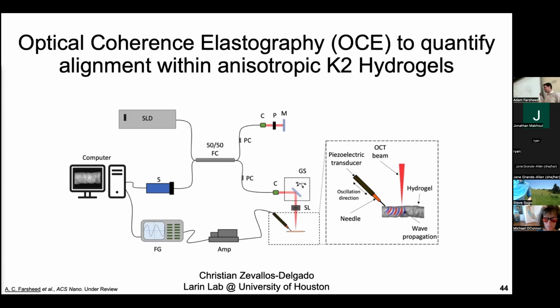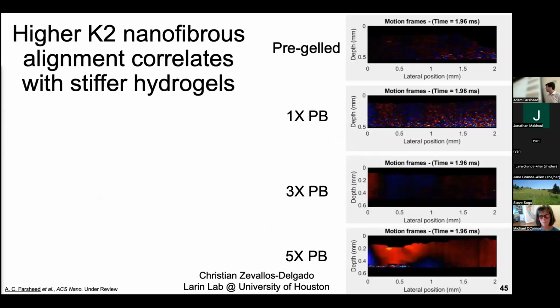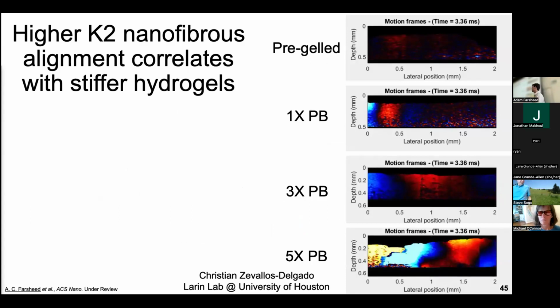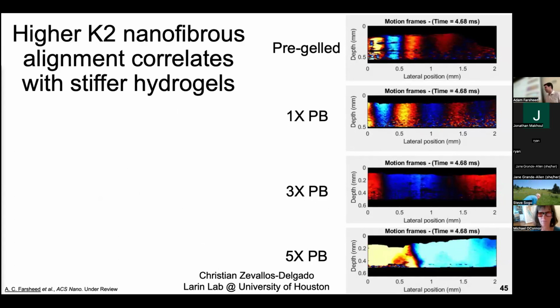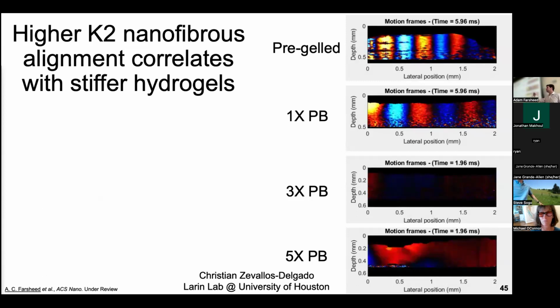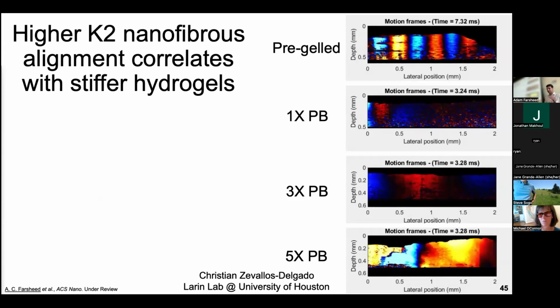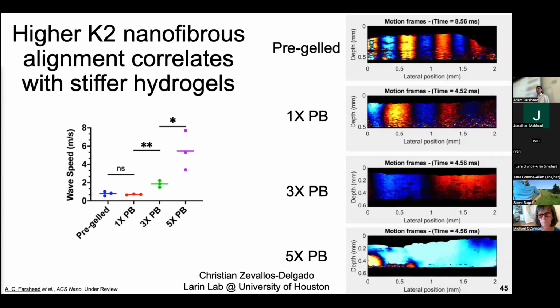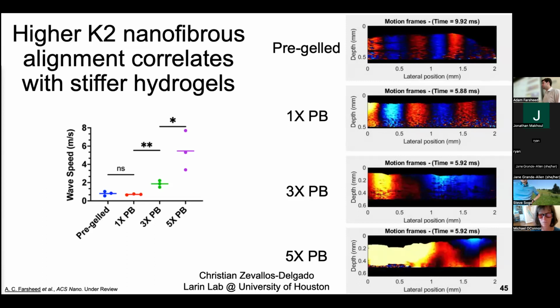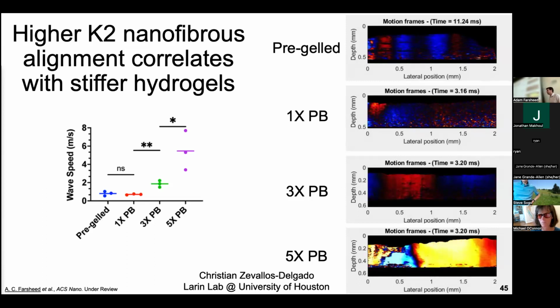And so what this technique does is it's a non-contact method of assessing the mechanical properties. A wave is basically shot through your sample, and you're able to observe that wave as it propagates through your sample. And you can correlate the speed at which the wave is moving with the stiffness of your material. And so I'm going to show a bunch of videos on the right here from pre-gelled down to the 1x, 3x, and 5x case. And what I want you to realize, in addition to the colorful nature of this method, is how the waves are moving faster and faster the further you look down our materials. And so we can quantify this data as the wave speed as a function of our different material systems and see some pretty drastic differences in the wave speed.